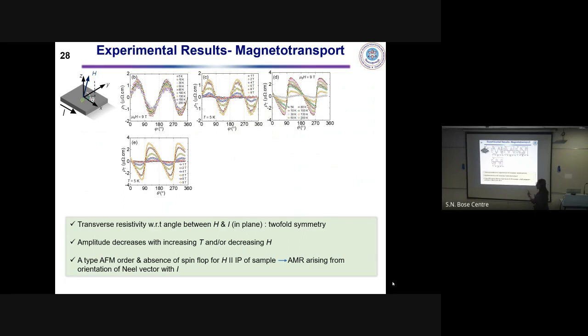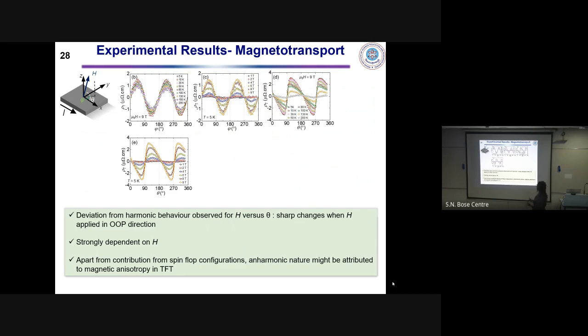Now, what is theta? Theta is the angle between H and the sample plane, as H moves from the in-plane to the out-of-plane direction. What we have observed, here and here also, is a deviation from the harmonic behavior seen for phi. We see sharp changes in rho t, and it is strongly dependent on magnetic field, but only weakly dependent on temperature. So if we neglect the contribution from the spin flop configuration, this anharmonic nature might be attributed to magnetic anisotropy.